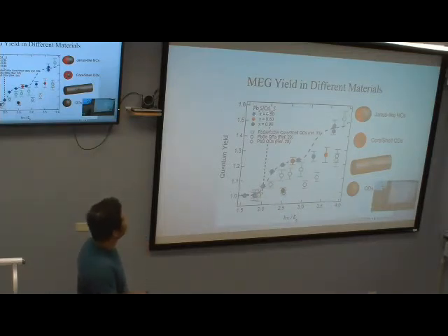And they synthesized three different quantum Janus structures. One is 50-50, 50% lead sulfide and 50% cadmium sulfide, and another is 60% lead sulfide and 40% cadmium sulfide. Another one is 90% lead sulfide, but that is very close to lead sulfide quantum dots, so they weren't able to calculate everything. The blue lines are mainly for the 50-50 one.